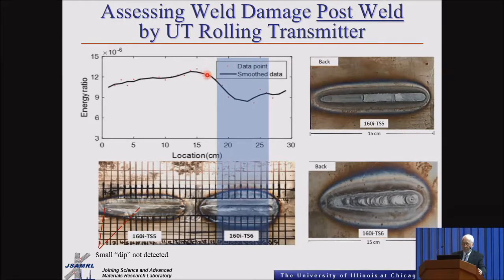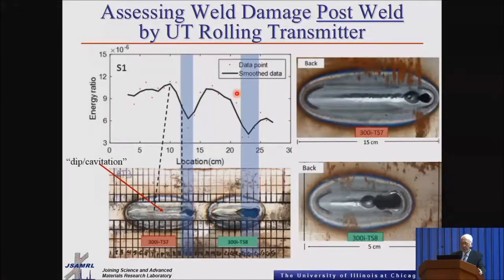You can see here, for this particular weld, we didn't see any burn through. Your signal was pretty much straight. Now, when it came to the onset of burn through, as I mentioned to you, you can see here some cavity, some depression in the weld metal, and that shows here as a drop in the energy ratio. This one shows no burn through, and this is the back side of the weld, no burn through, which goes with the signal right over here. But in this case we have the onset of burn through, or burn through. You have this depression, and you can see this drop in the acoustic energy ratio.